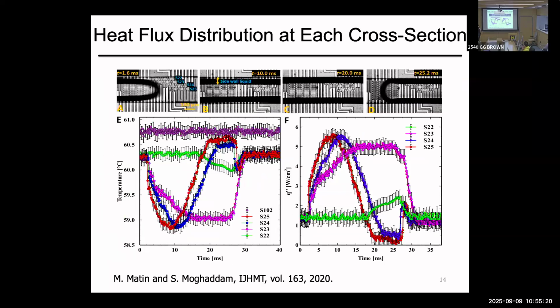So there was a question in the literature that the contact line has a very high heat flux relative to the rest of the surface. So we actually put sensors here. As you can see, as the tip of the bubble moves over the surface, all of these three sensors, 1, 2, 3, where they experience the thin film, the temperature drops. Sensor 2 is really where the contact line is, and you don't see an outsized heat transfer. And I discussed that in my 2009 paper, that even though that heat flux is high, it's over 0.3 micron, so it cannot really have an outsized impact on the heat transfer itself.